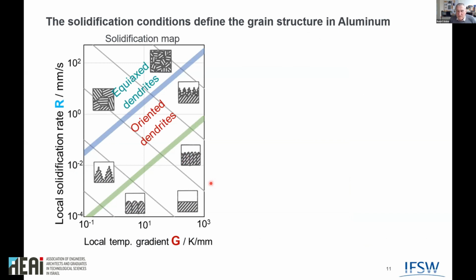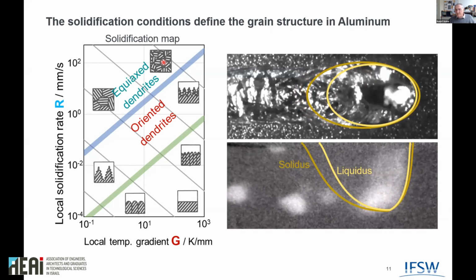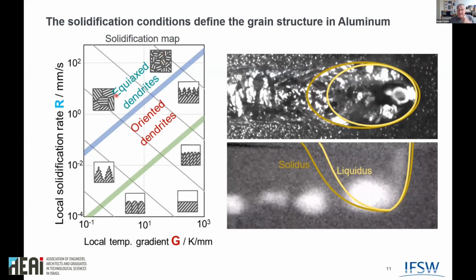To understand how to solve the problem, you must do some material science, very simple, just a short look at the solidification map. Here is the solidification rate, R, in millimeters per second. Here is the local temperature gradient, G, in Kelvin per millimeter. And then you can create such a map where you see that in this part, we get equiaxed dendrites, and in the lower part, we get oriented dendrites. So if you want to have strong, stable welds, we must come into this range here. And the question is now how to get there.